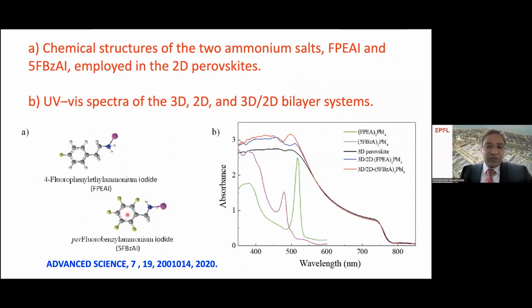Remember that fluorine-substituted cations are hydrophobic. Some of our materials are hygroscopic, they tend to take up humidity. So we want to prevent these hygroscopic properties by introducing hydrophobic cations. That's pentafluorobenzylamine, and here I have reduced the pentafluoro to monofluorophenylethylamine. Using these two cations, we made the two-dimensional perovskites shown here. The purple one is the pentafluoro, and the green one is the monofluorophenylethylamine two-dimensional perovskite absorption spectrum.